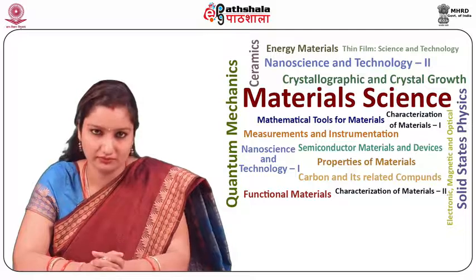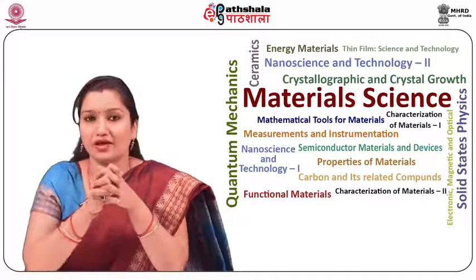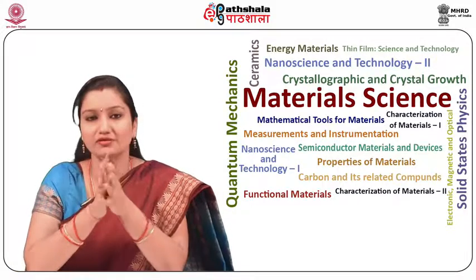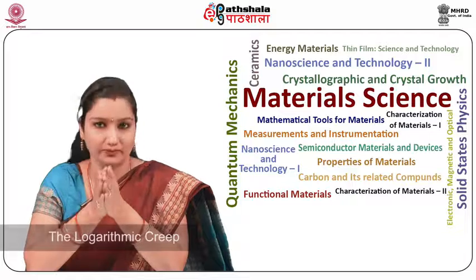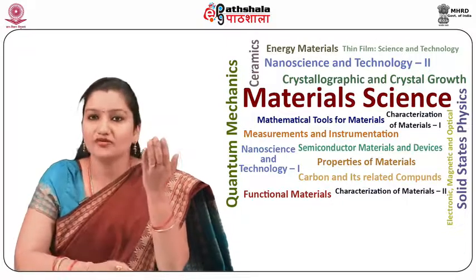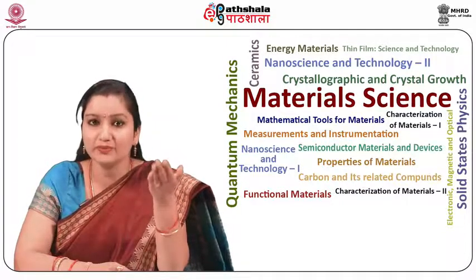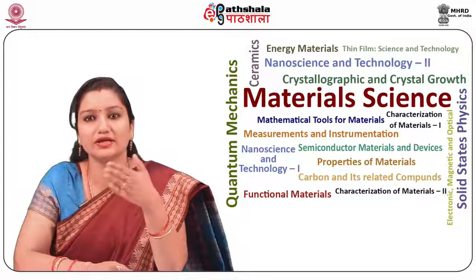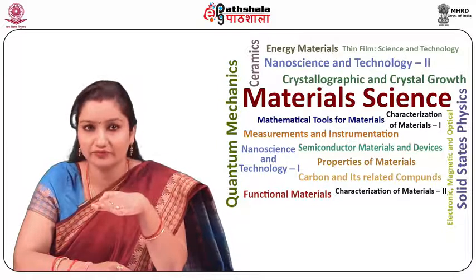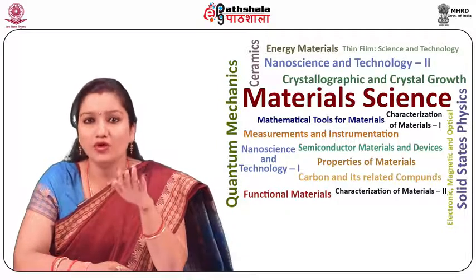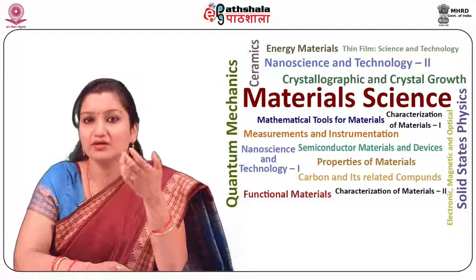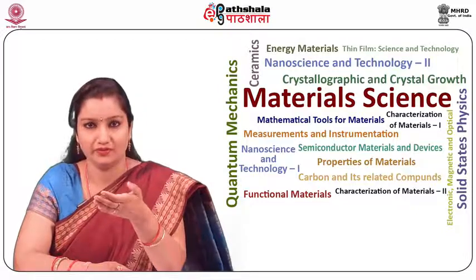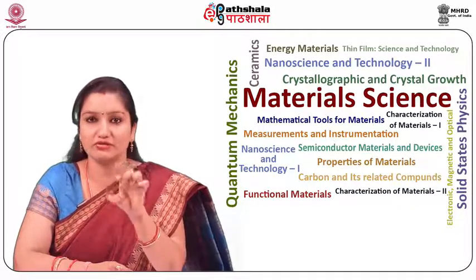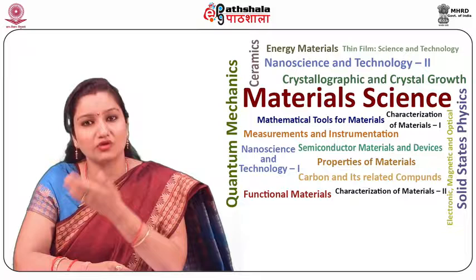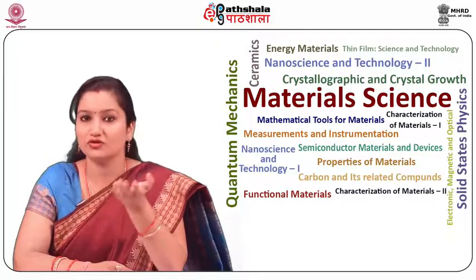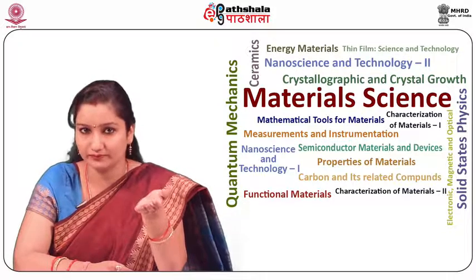Now students, let us study the types of creep depending on the temperature. The first classification of creep is logarithmic creep. At a low temperature, the creep rate usually decreases with time, and one obtains a logarithmic creep curve. So the first classification depending on the temperature is logarithmic creep, which is at the lower temperature.